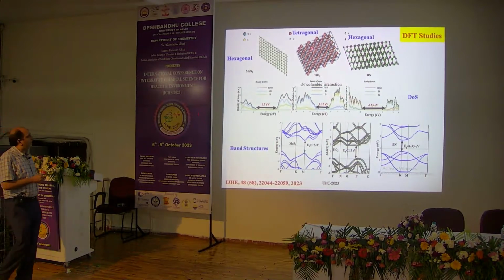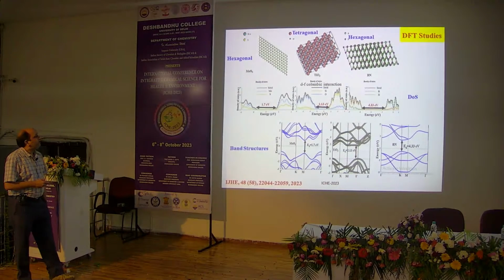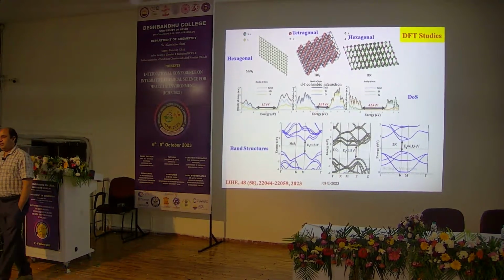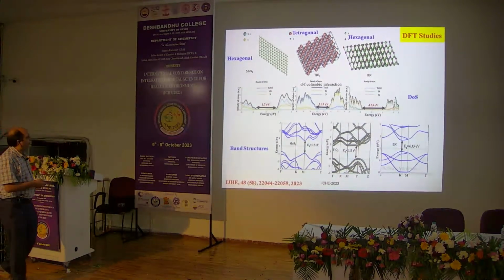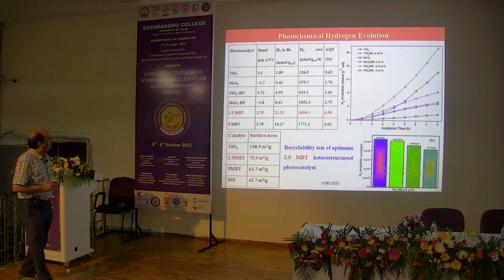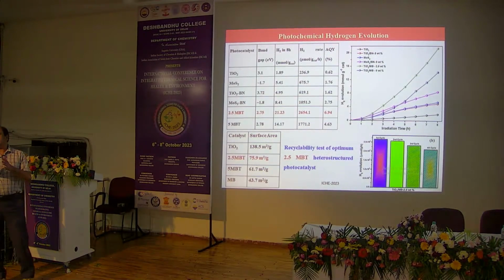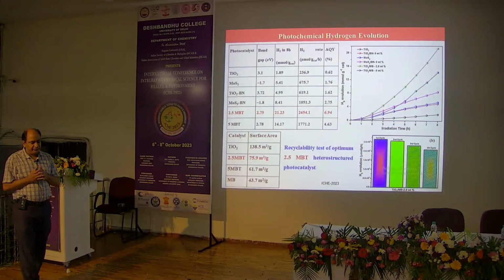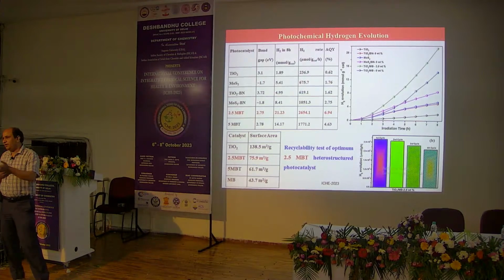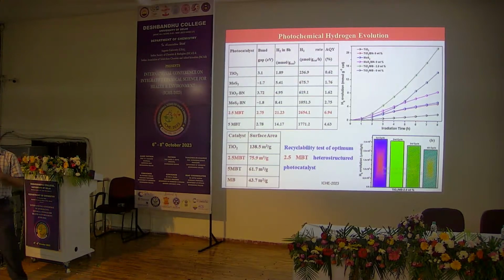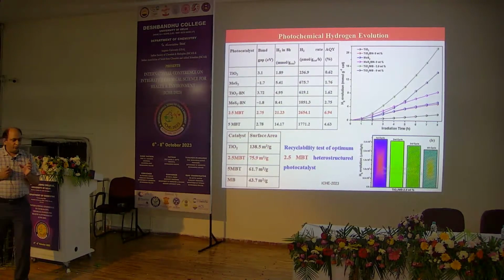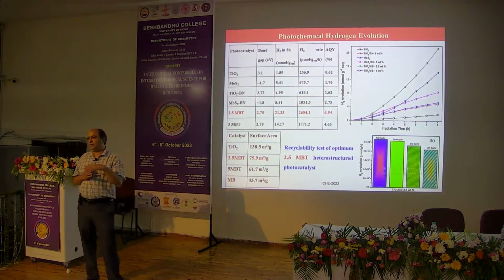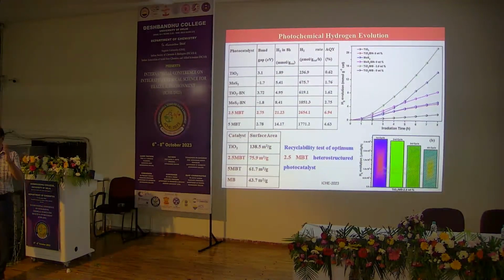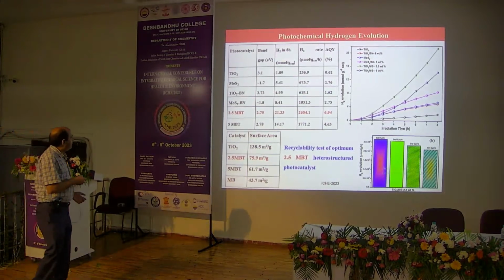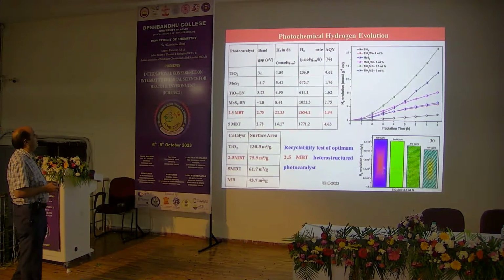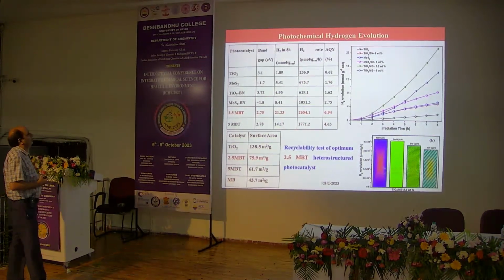The structure of the TiO2 was the same as we have in the X-ray diffraction, but the optical band gap was underestimated due to the DFT Coulombic interaction, and the similar band structure we also obtained. This paper is published in the International Journal of Hydrogen Energy. So we did the photocatalytic hydrogen evolution for these heterostructures. We applied it for the monophasic, binary and the ternary, and these ternary phases we prepared for the 2.5 weight% loading of MoS2 boron nitride over TiO2, then 5 weight% MoS2 BN over TiO2, then 7.5, and this 2.5 MBT could give the significant result of the hydrogen production, which was around 2.7 micromole per gram per hour.